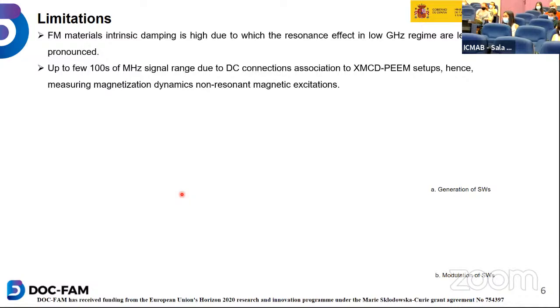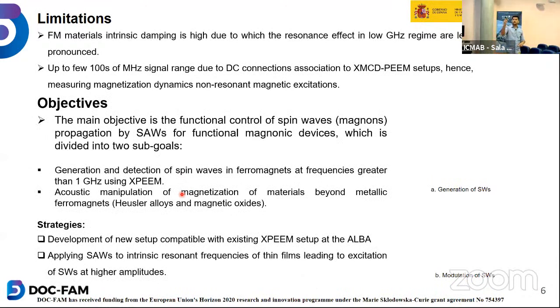Actually, the thing is that we are going to excite the intrinsic resonance frequency of the ferromagnetic material with a magnetic field. We do it outside, and then we are going to match the intrinsic resonant frequency of the sample and apply the signal at the same frequency. If you see, for example, this is the spinning, this is the precession. When you precess at a non-matching frequency, it will not give a high amplitude, and the damping will be quite fast. But if you do the precession with the same frequency, it will precess for a longer time, and the damping will be low. So this is our plan.